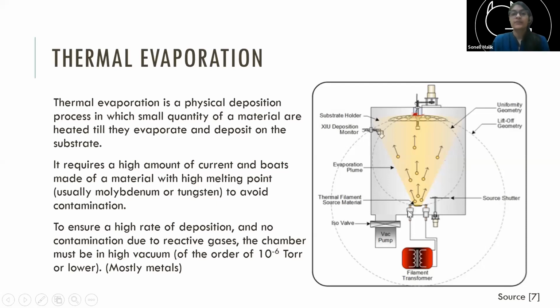There are these boat kind of structures on which you can keep the pellet. And these boats are usually made of molybdenum or tungsten. These are materials that have a high melting point, so that when you heat them up a lot, because the boat also heats with the material, it doesn't melt, or some of it doesn't evaporate by itself and get mixed with the substance that you want to deposit. And you pass a very high electric current across your boat, and because of Joule heating, it heats up, which also heats the material that you keep in the boat, and it evaporates.